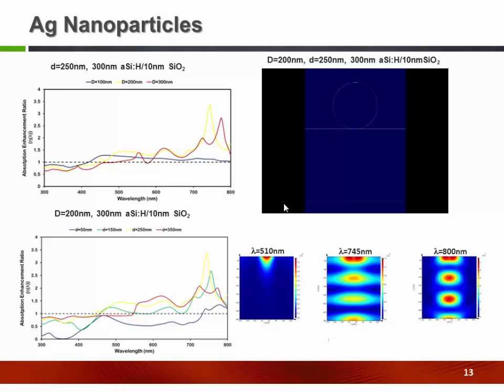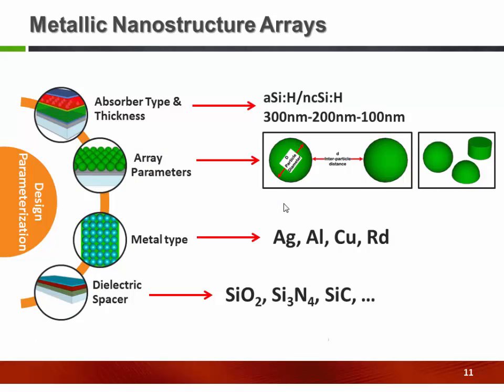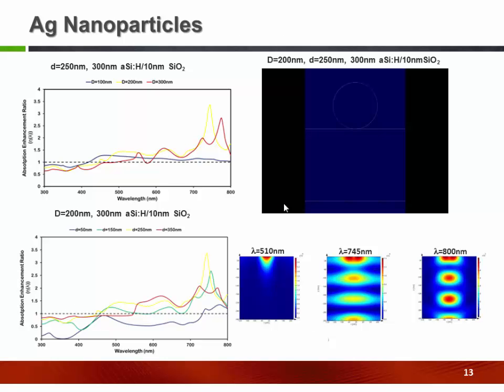Right. So I was wondering, how does that actually result in increased absorption? When the intensity of light increases, imagine, for example, you have 100 watts of light and now you have 1200. It looks, very simply, like instead of using AM1.5 light, you're using AM1, because the number of photons increases due to the resonance effect. But this happens locally, at a specific wavelength. This shows the increased efficiency due to the increase in light absorption intensity and the forward scattering. All of these phenomena happen at the same time, but the most important are forward scattering and the light concentration increase.